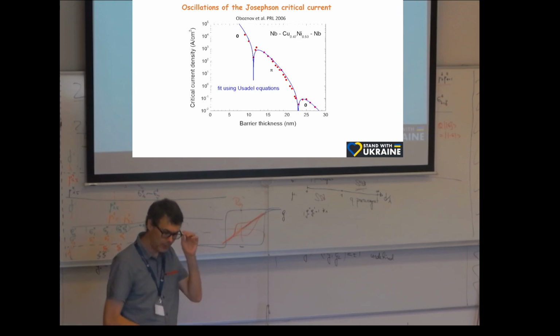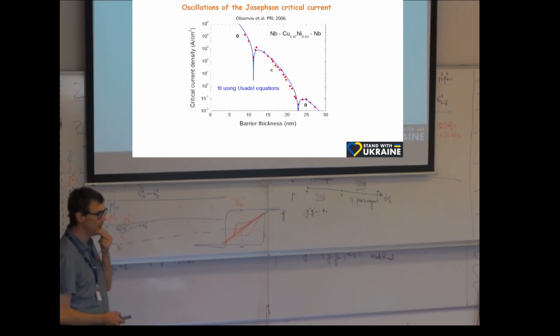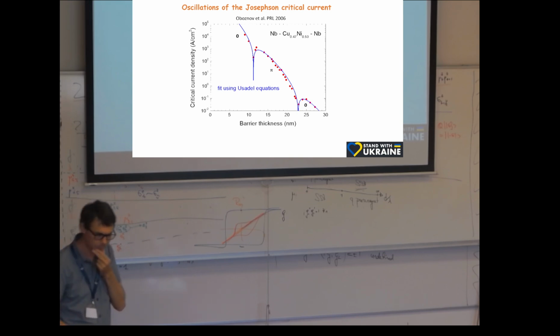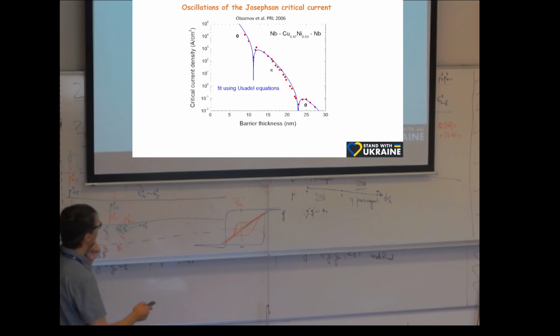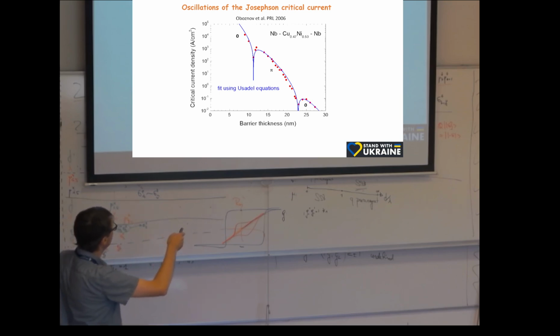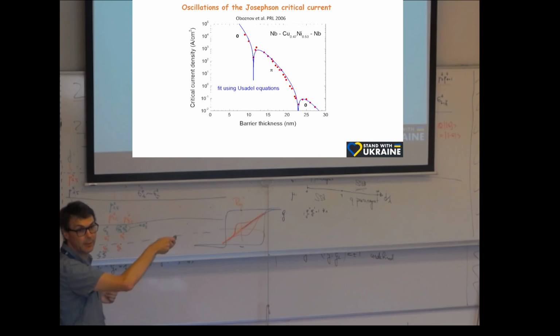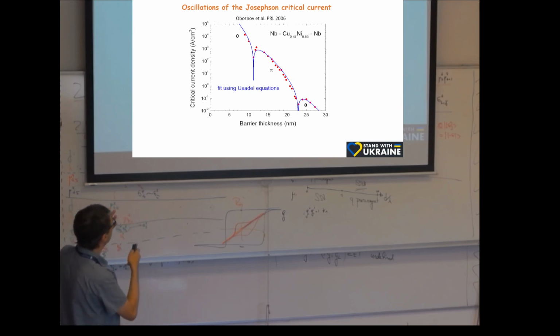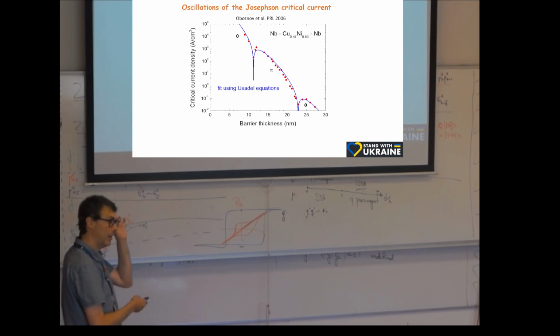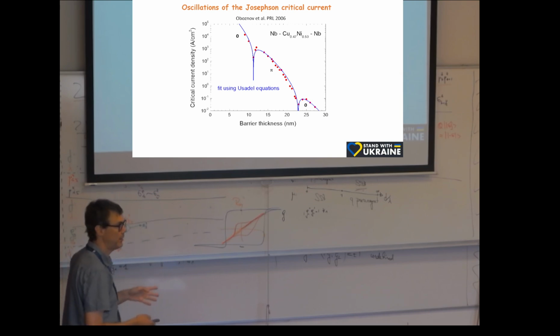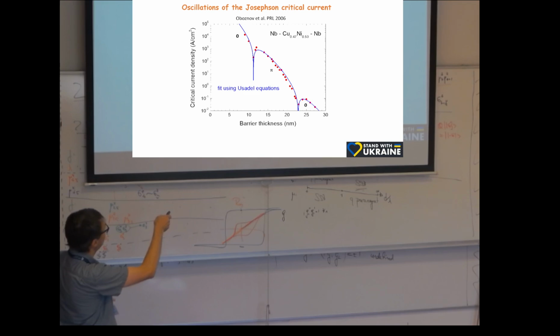Okay, and this is a beautiful effect. I think a bit fine-tuned data, but still, mostly this is exactly what happens. So you see the oscillation, right? And this is as a function of thickness. So Oboznov made these tri-layer junctions of different thicknesses, and he was mapping out the critical current, the maximum current. Hopefully he did it at the same temperature, but I think not quite. He kind of went to the maximum.